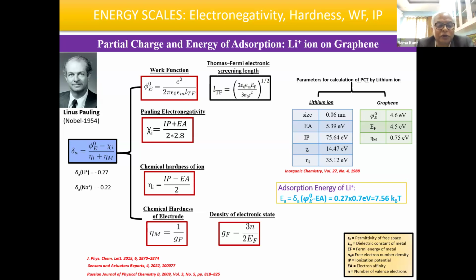So the fractional charge of adsorption is the ratio of the difference between the work function of my electrode minus the electronegativity, Pauling scale, divided by the chemical hardness of this ion and electrode surface. And the chemical hardness of the electrode is related inversely to the density of electronic states. So this formula indicates that. And then here we have listed some of these properties. Your electron affinity for lithium ion is 5.39 electron volts. Similarly, you have ionization potential. Because of charge, the ionization potential is very high. Then you have electronegativities and hardness.